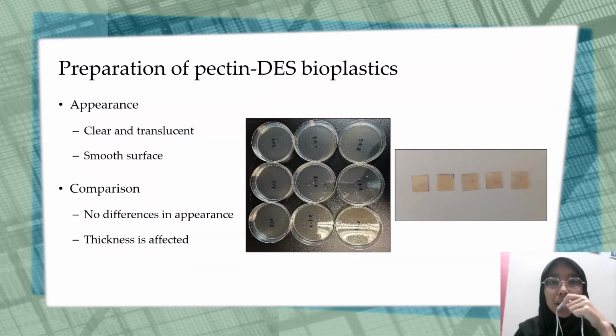The produced pectin-DES bioplastics have clear and translucent appearance with smooth surface, as shown in the figure. For comparison, different bioplastic samples have no differences in appearance, but samples with higher citric acid concentrations were thicker.